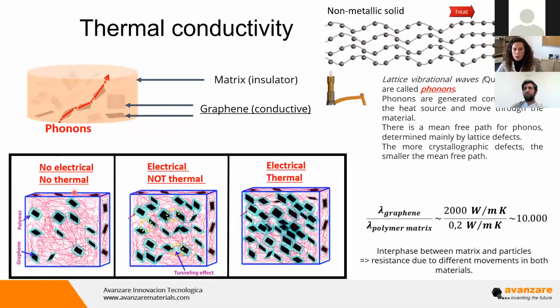So there is no electrical or thermal conductivity. In the medium situation, we are in the situation that is usually called percolation threshold. And here, the electrons can move from one layer to another because of the tunneling effect, in case there is not perfect contact between the layers. So we have electrical, but not so much thermal conductivity.